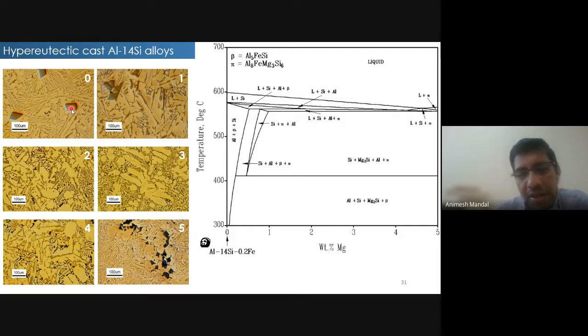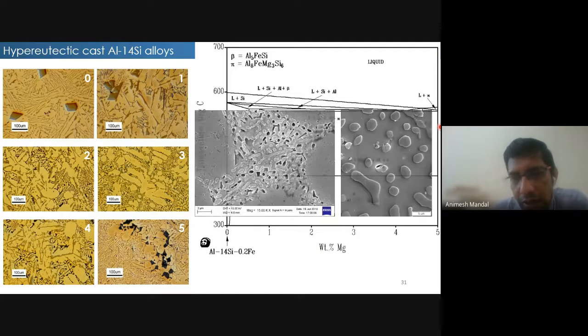Indeed, you could see that if you keep on adding magnesium to this hypereutectic aluminum silicon alloy, there is a complete suppression of this primary silicon. And that was something we were aiming at, because in that case you can have the alloy with a reasonable strength and also very good ductility. The reason is that you are suppressing the primary silicon.